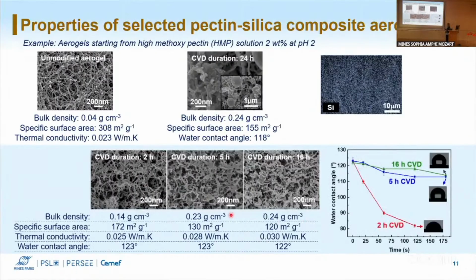But when we look at the contact angles over time, we see that with 2 hours of deposition, the contact angle decreases a lot and the droplet is eventually absorbed by the material.